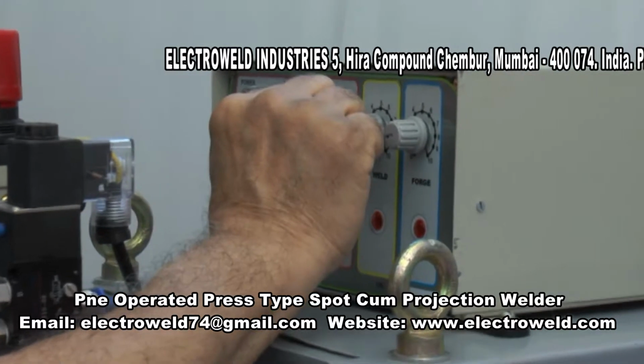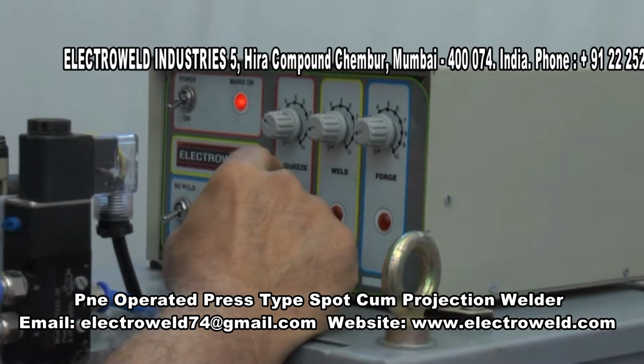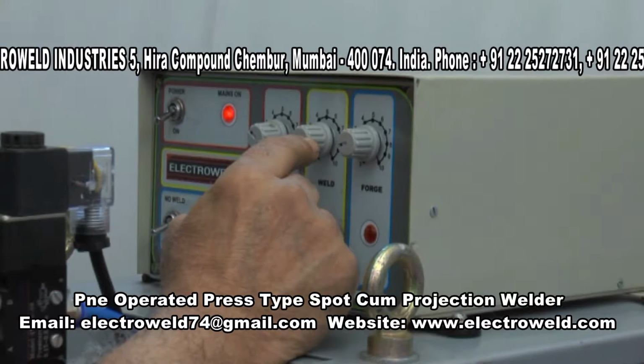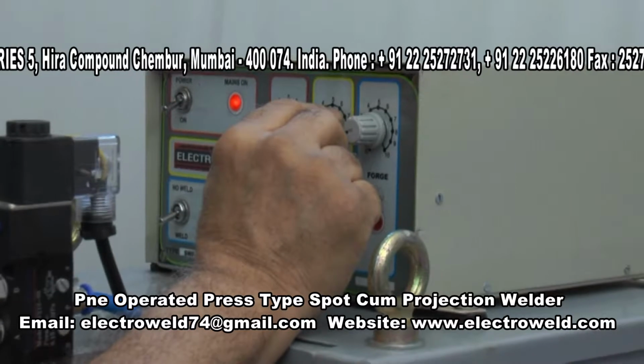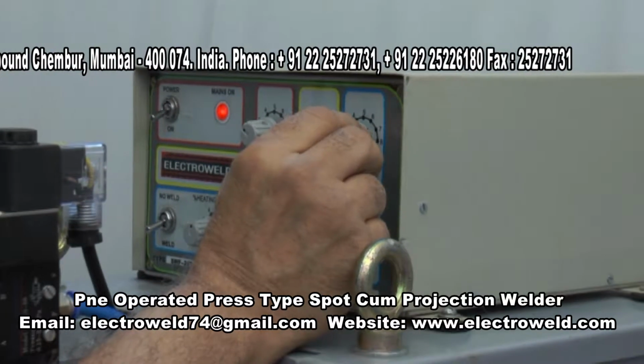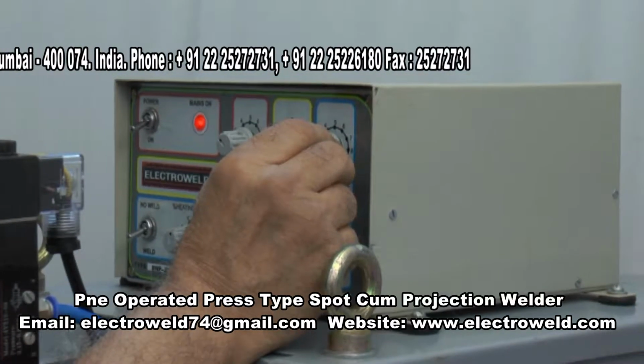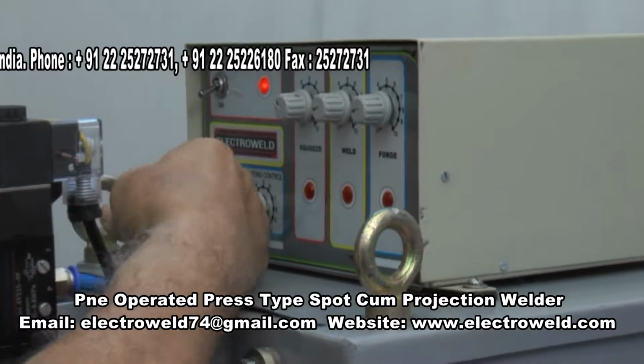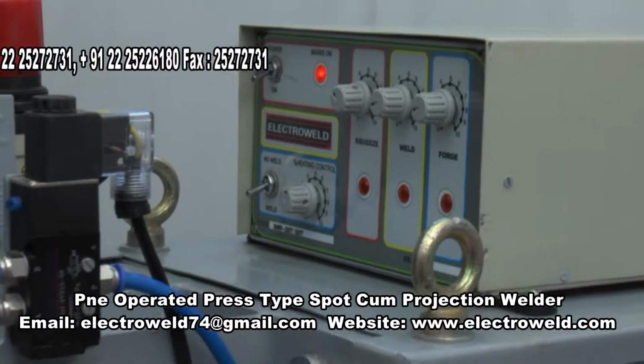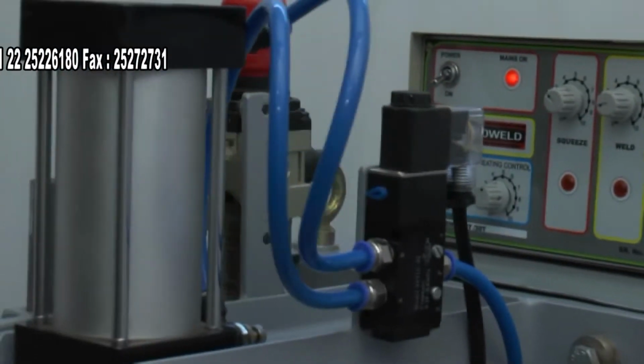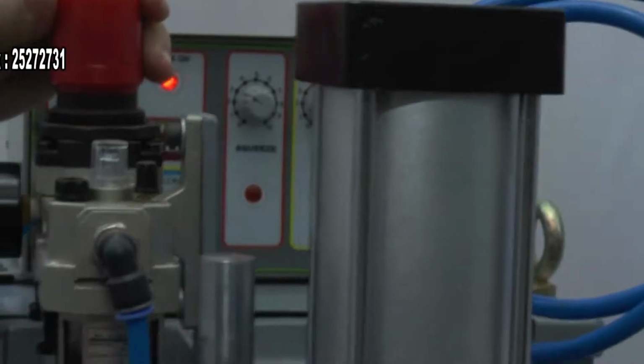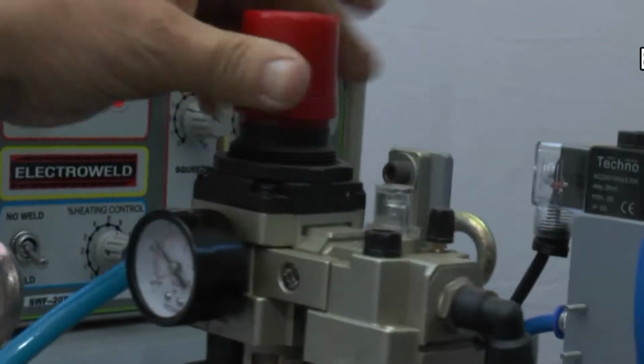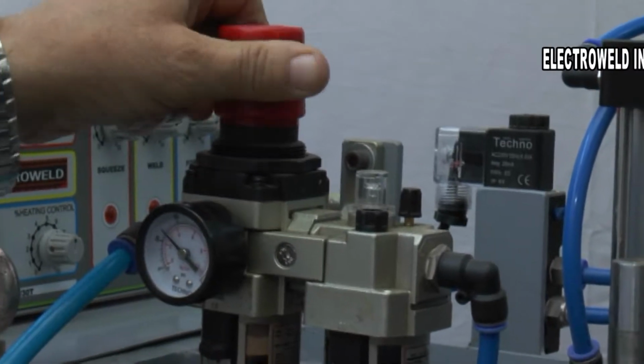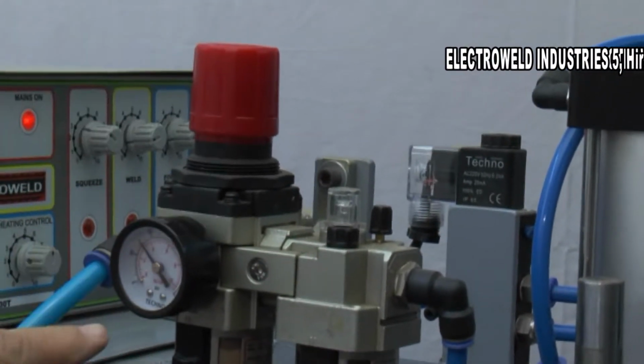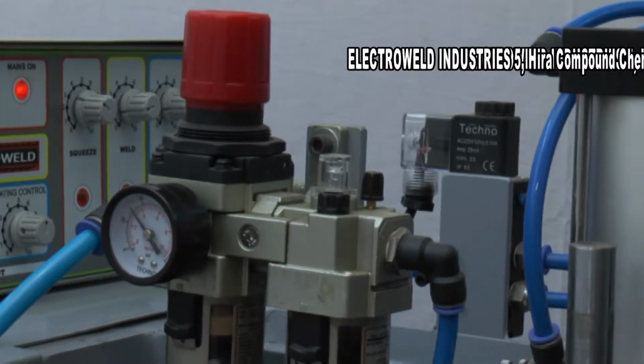Then squeeze time keep at number 3, say about 30 cycles. Then the weld cycles you can keep at number 10, and the forge cycles you can keep at number 10 cycles, and then switch on this no weld switch like this. Pressure over here you can keep for 2 mm plus 2 mm sheets at about 40 psi. Now the machine is ready for spot welding.